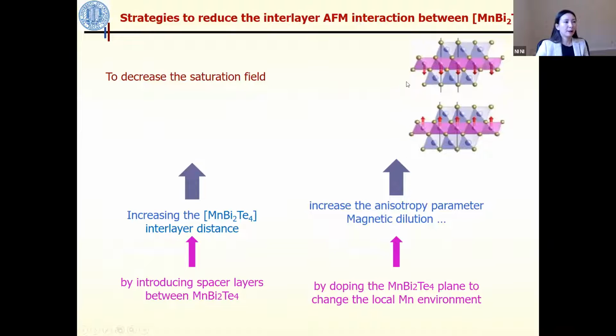Okay, so before we go forward, this material has uniaxial anisotropy here. The saturation field depends on the interlayer exchange interaction and the magnetic crystalline anisotropy, right? So you can see there will be 2 strategies, which means you either tune the exchange interaction or you tune the magnetic crystalline anisotropy. So this is the crystal structure of the 124, right? One strategy is to increase the distance between these 2 layers, right? By increasing the distance between these 2 layers, you will be able to reduce the interlayer exchange interaction, right?